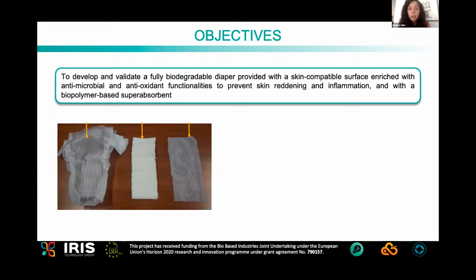During the project, we focused mainly on 2 different parts of the diaper. The first one is the top sheet, the layer that goes directly in contact with the skin. We formulated a PLA-based material that was then embedded with specific active compounds, because we also wanted to provide specific functionalities. The idea was to have antimicrobial and antioxidant properties. We achieved them thanks to nanocapsules made of chitin and lignin that were able to encapsulate different kinds of active molecules, and in our specific case, we selected glycyrrhetinic acid, an antioxidant and antimicrobial compound.